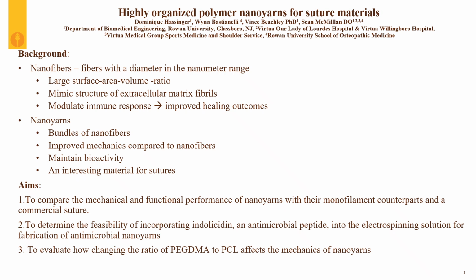These are fibers with diameters ranging in the nanometer range. They have a large surface area to volume ratio, making them really suitable for surface functionalization compared to their microfiber counterparts. They mimic the structure of the extracellular matrix fibrils, which allows for better cellular interaction, and they have been shown to modulate the immune response by polarizing macrophages from M1 to M2, which is pro-healing, and